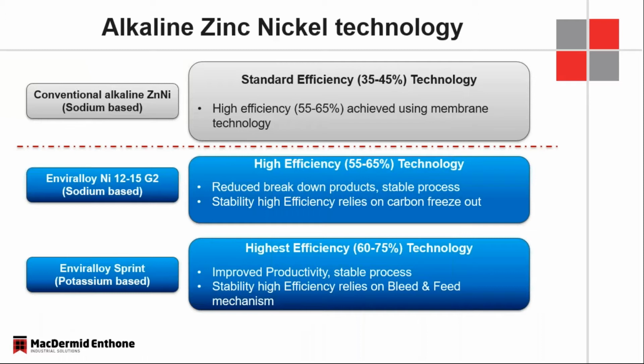So back in the sodium systems, we're looking at an efficiency of about 35 to 45%. When baths are used and made up brand new, they're going to be higher, and the efficiency is going to be reduced over time, pretty much because of sodium carbonate, but also to a little bit of a lesser extent, some of the breakdown products that are associated with the organic additives in zinc nickel systems. A few years ago, we improved our sodium systems to raise the efficiency to approximately 55 to 65%. But more than that, we were able to reduce some of those breakdown products.